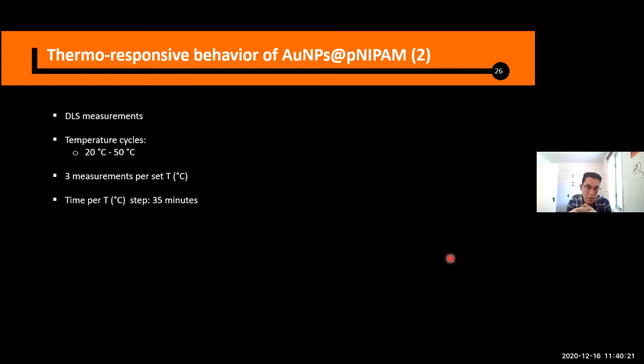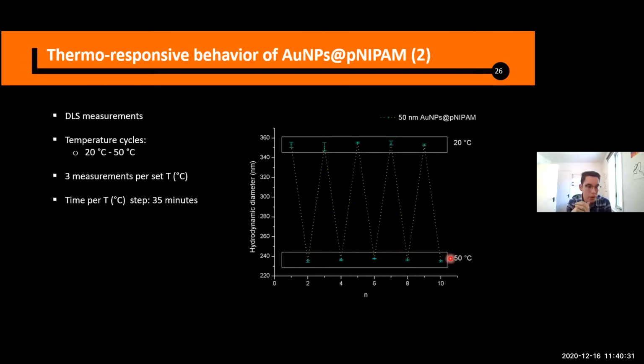And just to confirm that these particles are reversible, I performed some cycles between temperatures of 20 and 50 degrees Celsius. And this is what I obtained: I can switch back and forth between the swollen and shrunken states of the particles between 20 and 50 degrees Celsius in many cycles. And the particle size is kept pretty constant. So we can see that these particles have a very stable behavior.